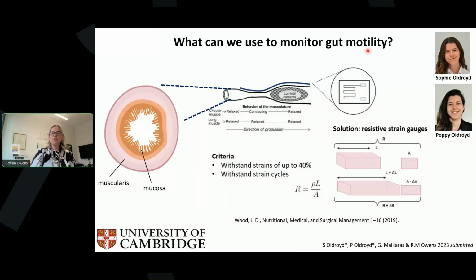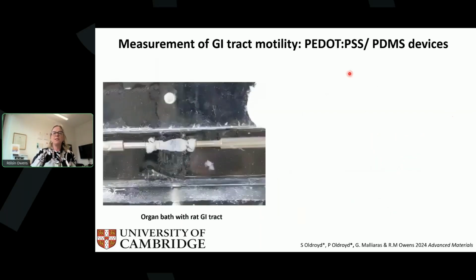So in terms of measuring gut motility, we've used a fairly simple device, which is a strain gauge, meaning that when you stretch this device, you increase the resistance, and when you contract, you decrease the resistance. And this has been well known. The trick here was that we needed to take our PEDOT:PSS devices, which I showed you earlier, and make them stretchable. And the stretch is quite large in the gut, so it can be up to 40%. So we had to show that that was possible.